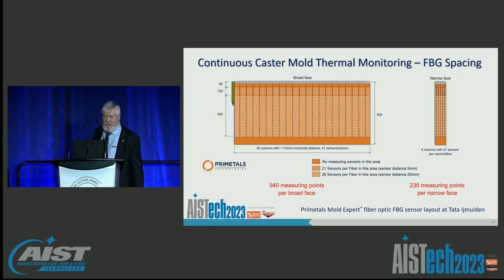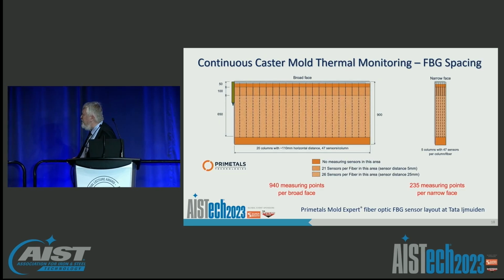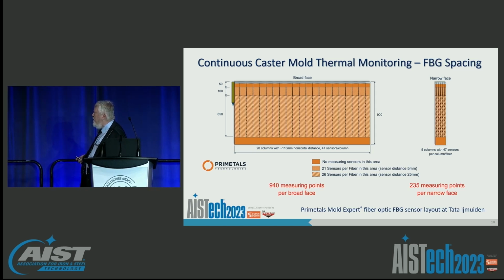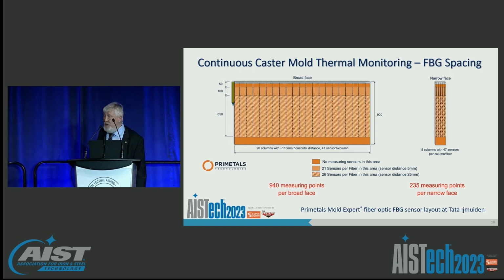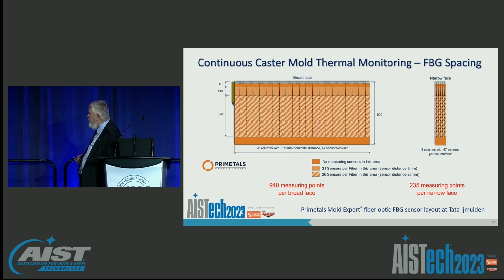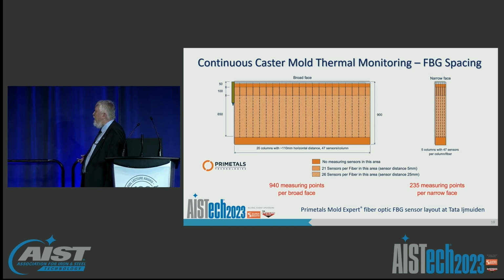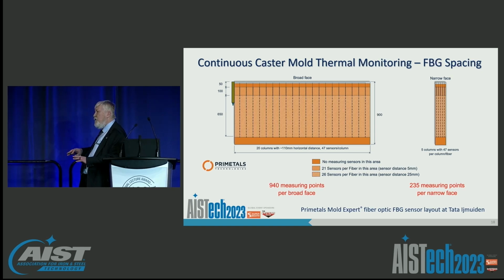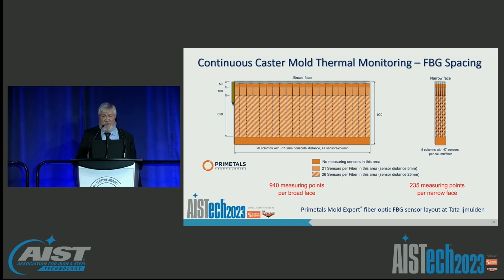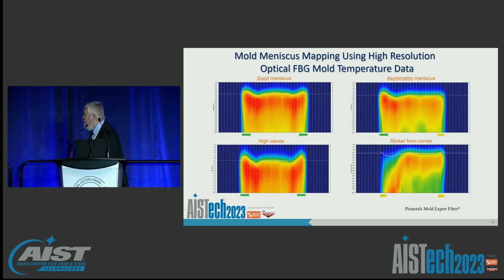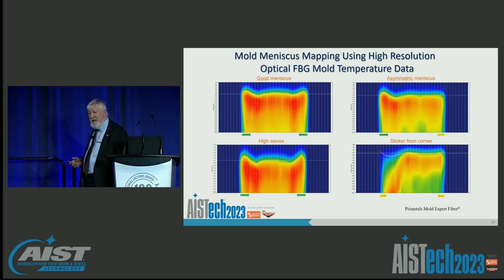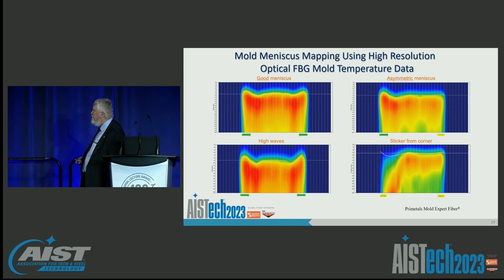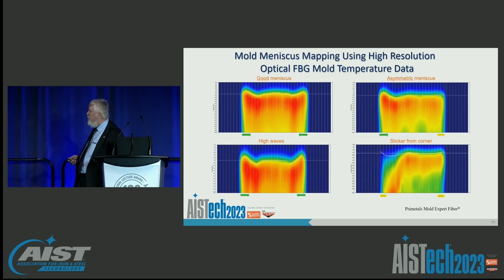There are others out there, and this happens to be one of the more higher resolution ones that I've seen. In this case, each area shaded actually is an individual fiber, and each fiber has between 21 and 26 sensors etched on it. Here they've actually mapped a much higher density around the mold meniscus area. And the advantage of doing that is we can now thermally trace the meniscus and the meniscus shape. And here are some examples of that. Here we can actually see standing waves, flow asymmetries, sticker events for sticker detection, but you can actually track and monitor that wave shape. And it can be tracked in real time.